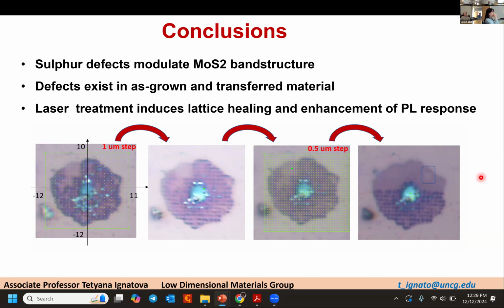I know. There's papers already out there that talk about how just any ambient, like water, I mean, even your breath, like your coffee breath that you had in the morning, will dope the system. And there are laser powers much lower than even the powers you were showing, 10 milliwatts, which is actually too much. Major experiments were done below 1 milliwatt. Even at 1 microwatt, you can actually already see desorption of species off the surface of MoS2 that will change the luminescence.